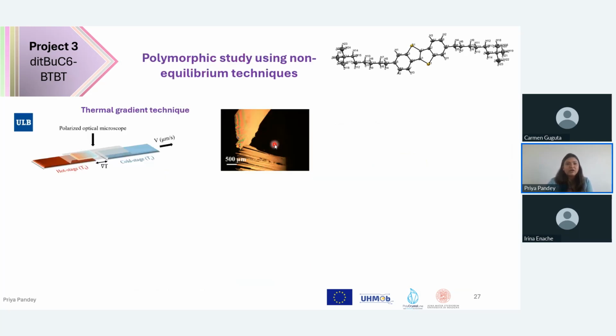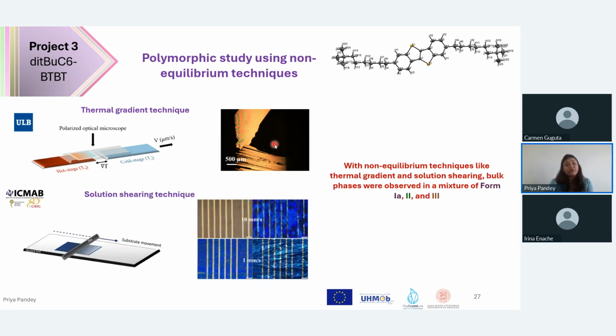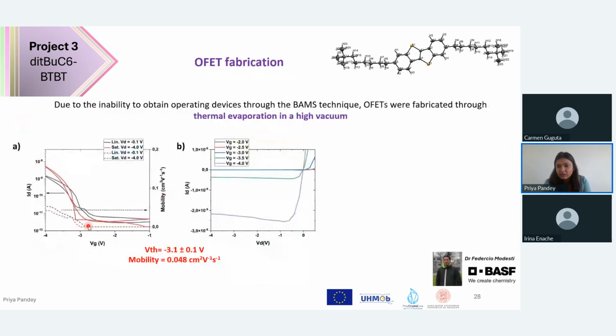Of course, after all the bulk conventional polymorph screening, I also tried this molecule for finding new polymorphs using non-conventional techniques. I didn't find a new polymorph, but I did find that it always exists in a mixture of form 1A, 2, and 3, which led to difficulty in fabricating OFETs using the solution shearing method, for which I turned to another project colleague, Federico from BASF.